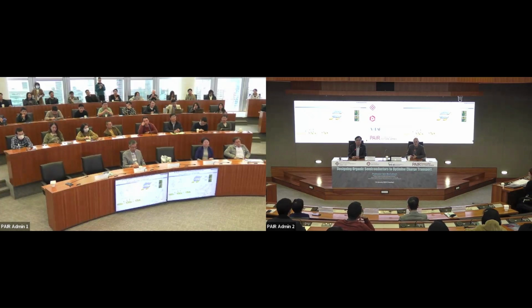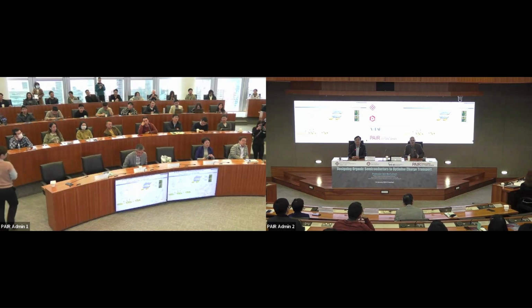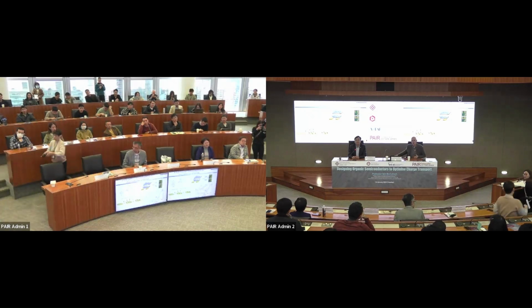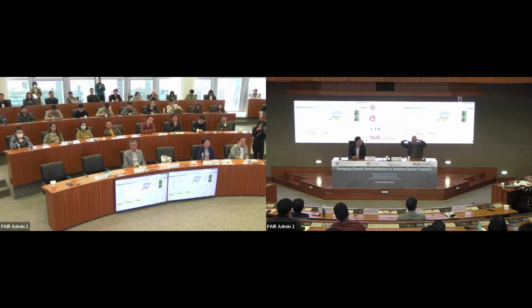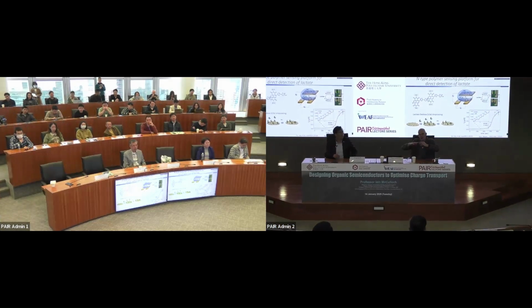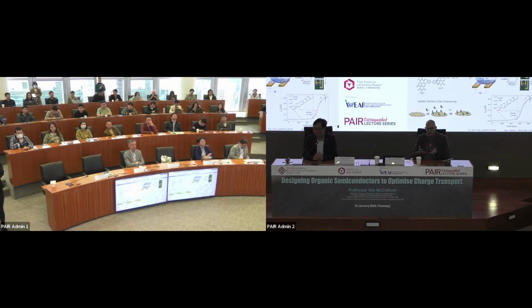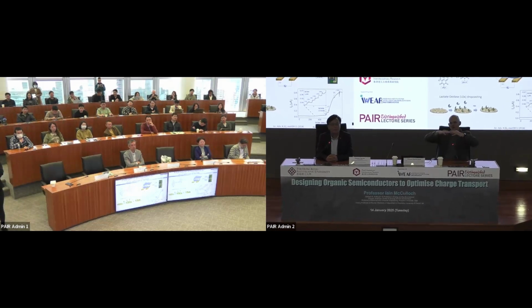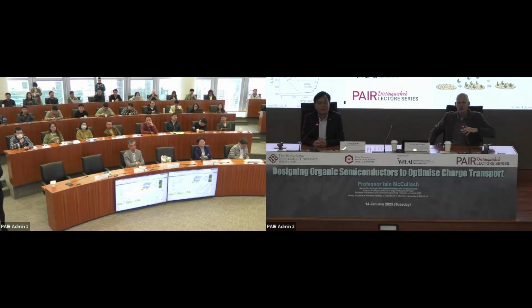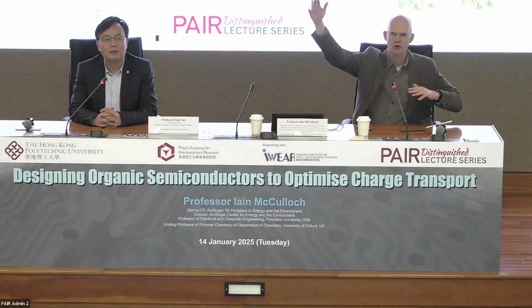So it forms a polaron. When you inject a charge into the semiconductor, it's a lower energy, spread-out charged species. It's a little bit like, imagine a bowling ball on a trampoline. At first you have your energy level, you throw the bowling ball in, it sinks down, and that sinking process determines the speed. If you have a semiconductor with low order or high disorder, the bowling ball sinks much deeper into the device. Whereas if you have a system that's well designed and coplanar, it's maybe like throwing a bowling ball on a marble floor. It bounces and it goes much faster.